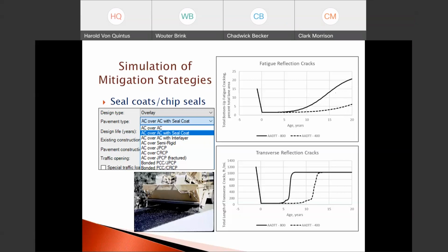That's true for both the top graph for fatigue reflection cracking, as well as the bottom graph, transverse reflection cracking. With the lower truck traffic, there is a delay, as we would expect, and then there is a longer time to propagate those cracks, both transverse and fatigue cracks, over a 20-year design. So truck traffic is important, as well as the thickness of the overlay.